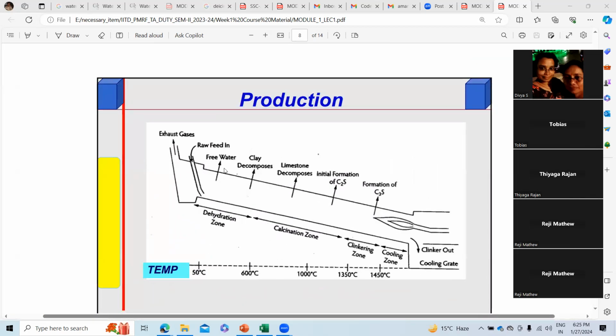We just make some ingredients. Ingredients means calcium carbonate, like limestone, silica, and clay shales. We put them together and burn them. Free water is evaporated, dehydration between 50 to 600 degrees Celsius. Then at about 550 to 590 degrees, clay decomposes, and in the calcination zone, lime decomposes. After lime decomposes, that's about 900.